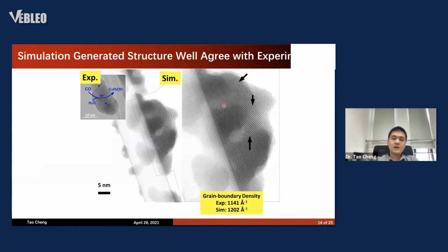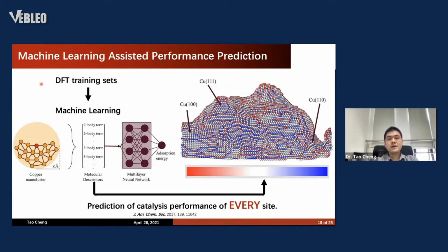And if we look at more details, for example, people all agree that the grain boundaries are very important for the activity. So we analyzed the grain boundary density from the simulation and the experiment. We can see that it's quite close. So this means that using this computational synthesis method, we can generate a nanoparticle structure that is very similar to the experimental result. And this gives us a very good starting point to simulate the nanoparticle. But then the problem is that the nanoparticle is too big. We cannot use the technology we developed just now to investigate all of this size, because that is too expensive.